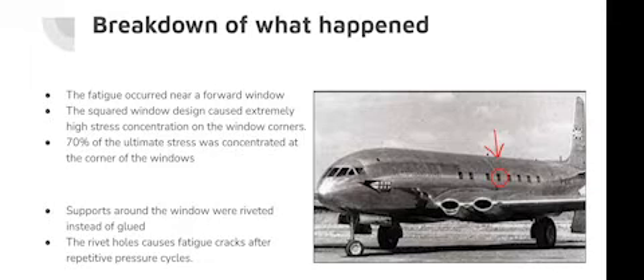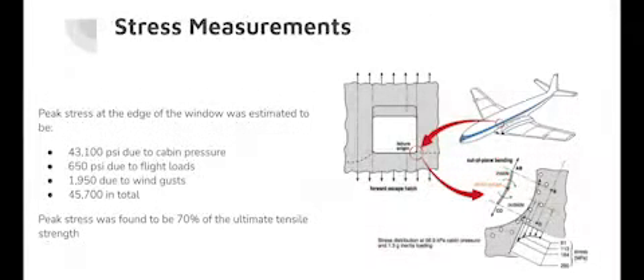The second severe issue was that the supports around the windows were riveted instead of glued as originally stated in the design. The rivet holes caused the fatigue cracks to occur because of the repetitive pressurization and depressurization of the cabin during flights. The sharp right-angle corners of the squared windows caused local areas of high stress concentration that provided optimal conditions for crack initiation and propagation.